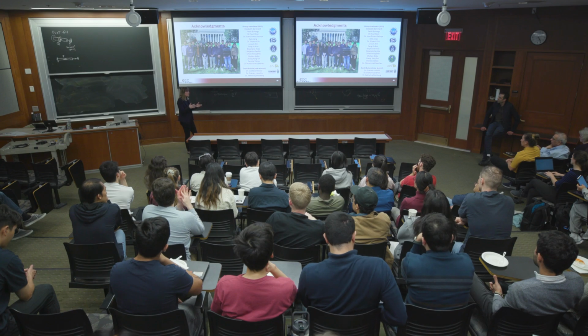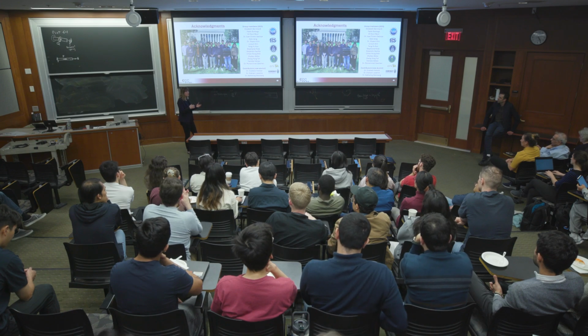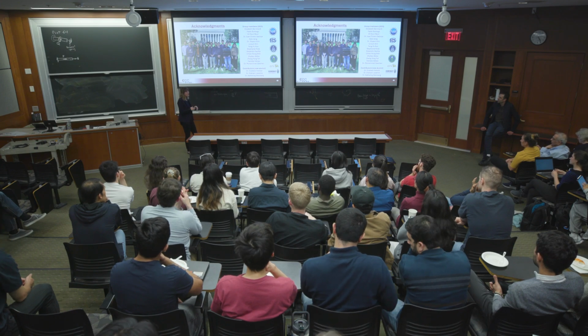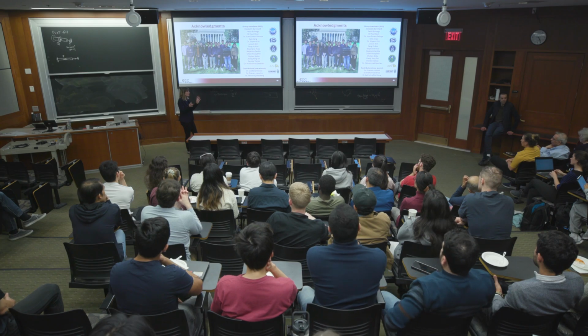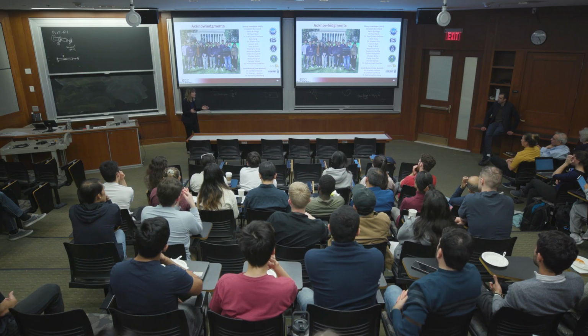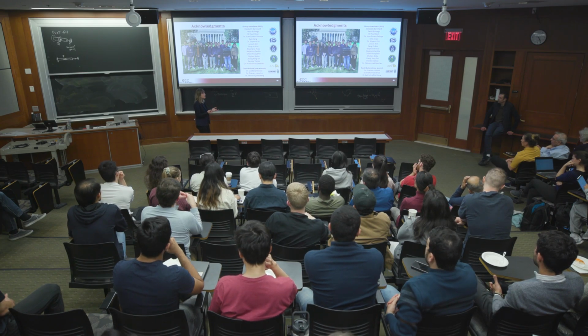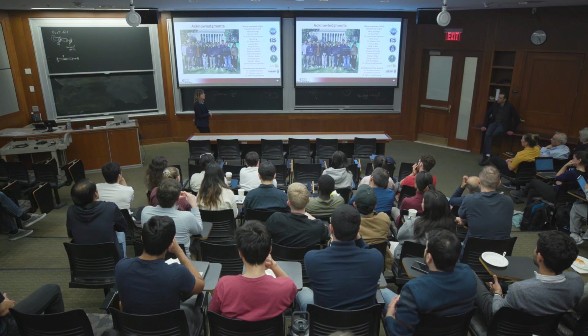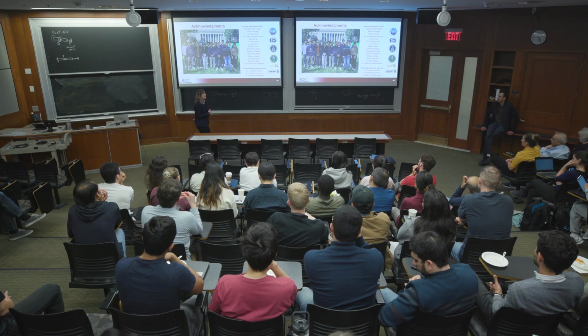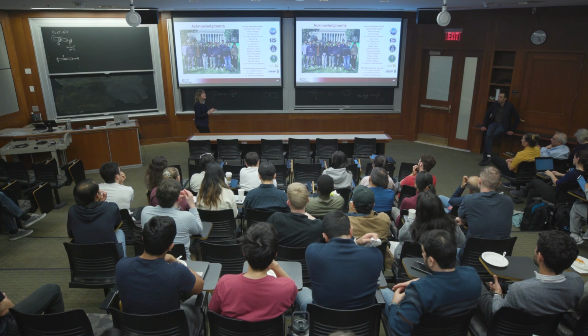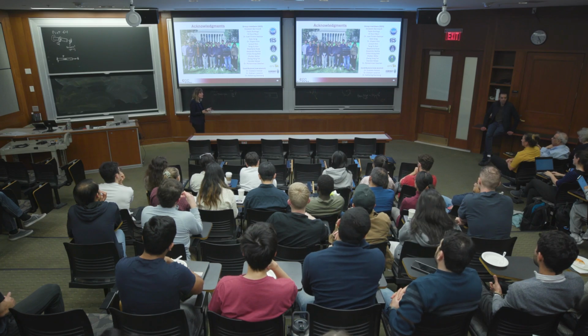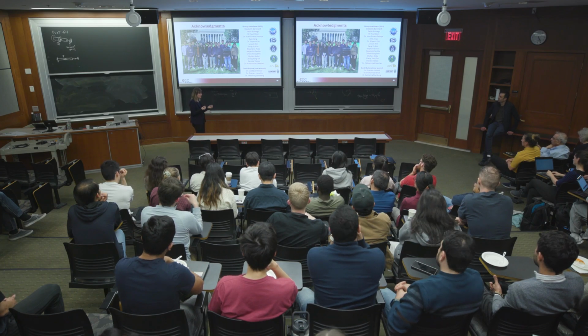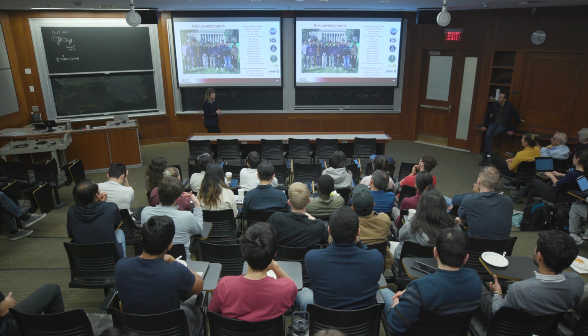So inherently, you have a solid-solid reaction in those cases, so the phases you form are different. The compositional landscape of solid electrolytes is different, so the phases that you'll form at that interface are going to be different from the case where we have solvent, for example, participating. But yes, the evolution of the interface leading to high impedance and then degradation, both in plane and then inability to cycle, is a major issue that people have been working on.